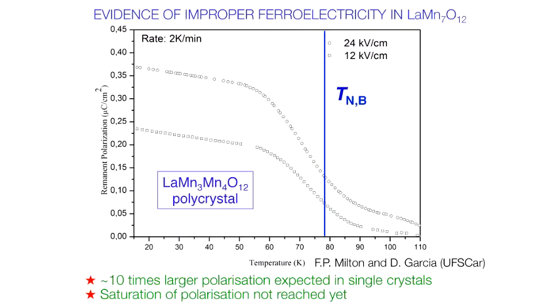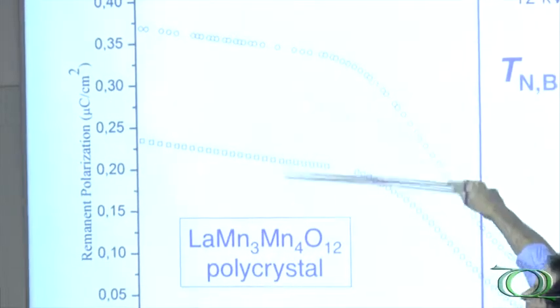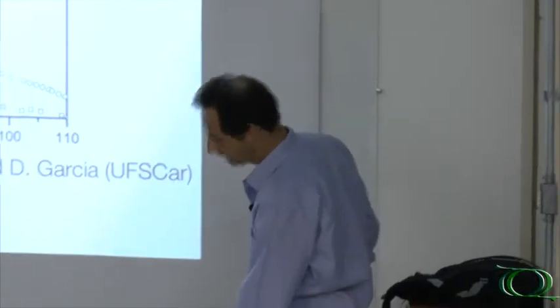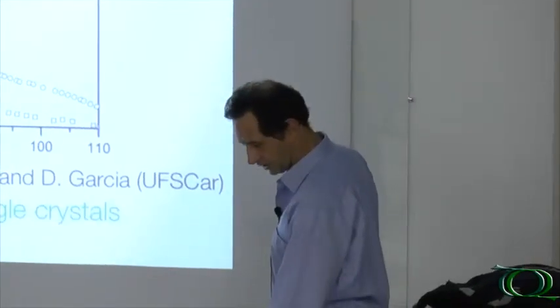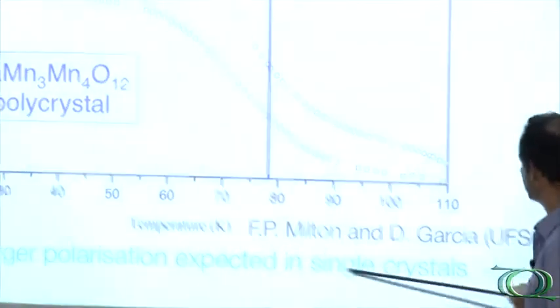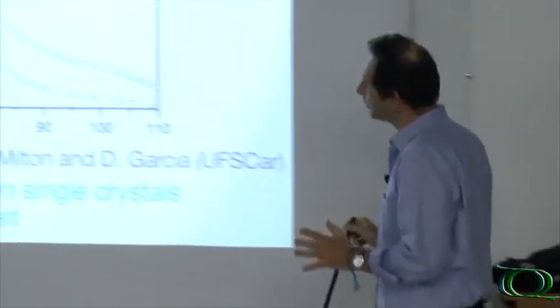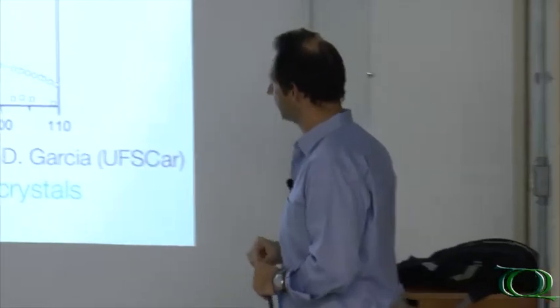Here in UFSCar, we started last year a study on the ferroelectric property of this compound because we thought they could be ferroelectric. These are data taken today. By varying the polarization, you have a remnant polarization which is a fraction of microcoulomb per centimeter squared, about 0.4 almost. By doubling the polarizing field, you increase almost by two. These are preliminary data. The polarization at saturation is probably in the one microcoulomb range. This experiment was performed by Flavio Milton and Ducine Garcia. We expect 10 times larger polarization in single crystals. This is the measurement of polycrystal. We didn't reach the saturation, so we can be conservative and say we can get one microcoulomb, if not 10 microcoulombs per centimeter squared.